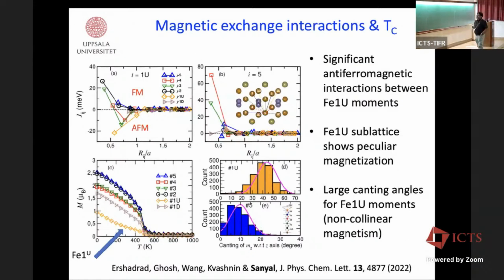This is rather a busy plot. So I said that now I will only show you here the isotropic exchange interaction parameters. The convention is that the positive numbers indicate ferromagnetic interactions. The negative numbers indicate antiferromagnetic interaction between a pair of magnetic moments, between a pair of iron atoms.